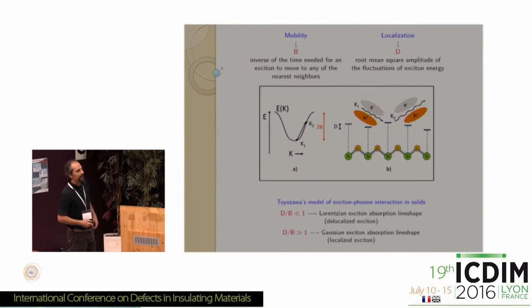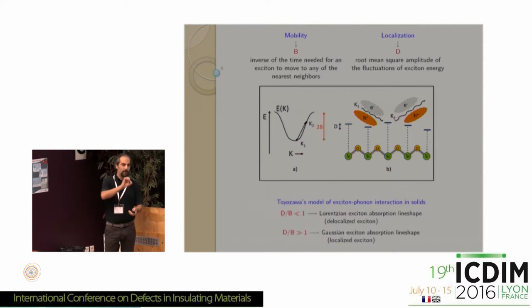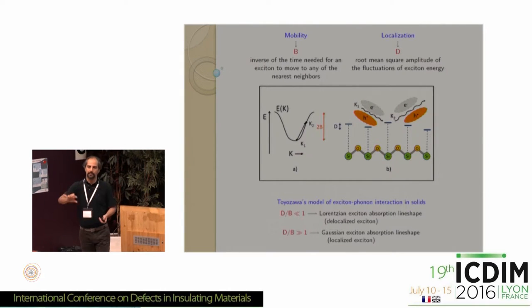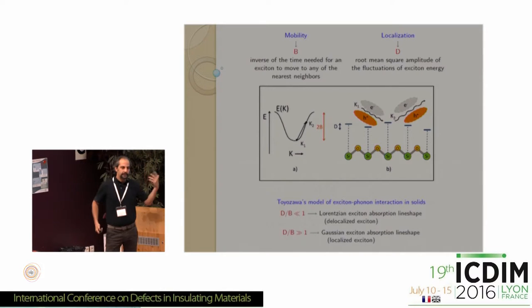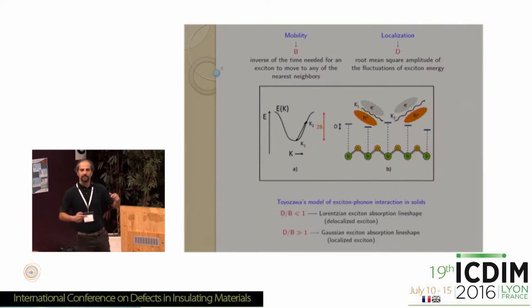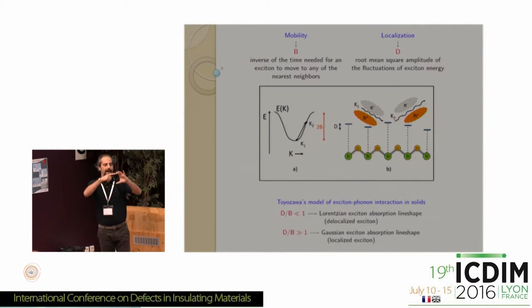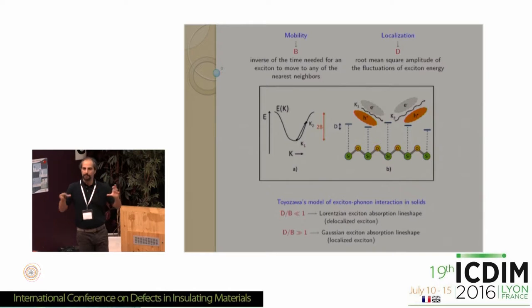Now, the mobility of an exciton can be measured, qualitatively speaking, by the time needed for an exciton to move from one site to the nearest neighbor site, okay? Or, in other words, the fact that the excitons are mobile from a theoretical point of view can be associated to the fact that you have a band of excitonic states classified as a function of their wave vector k, because they can move.